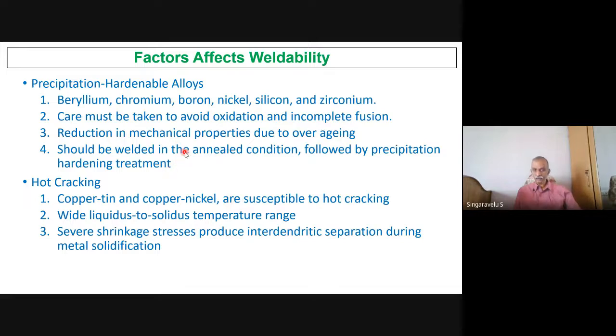This is the solution, right? Because alloys will deteriorate their own mechanical properties because of this aging. After over-aging, these precipitates will never come back to the original. So it will not form the precipitates. The precipitates are getting broken down. So that is called over-aging. So the better process is to weld in the annealed condition followed by the precipitation treatment.